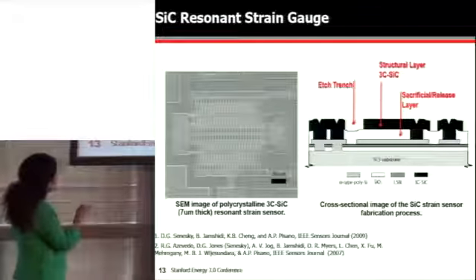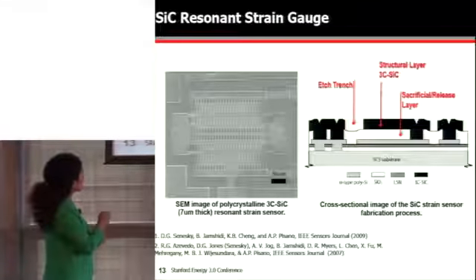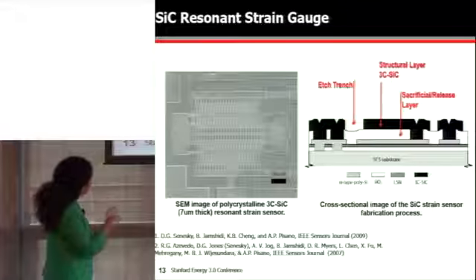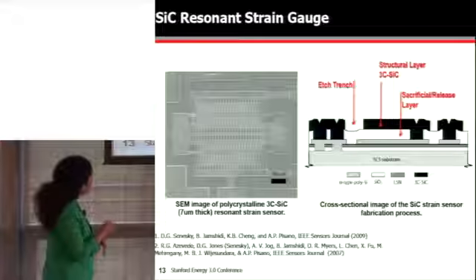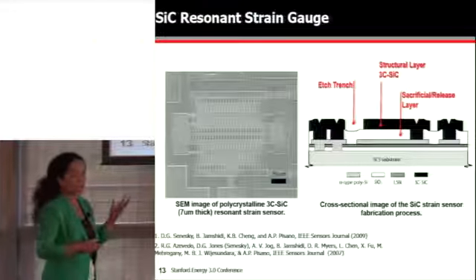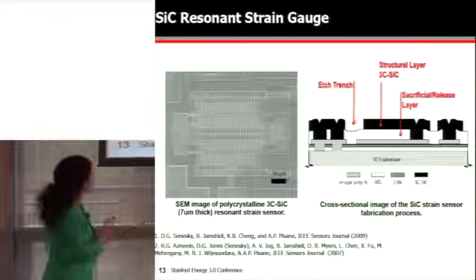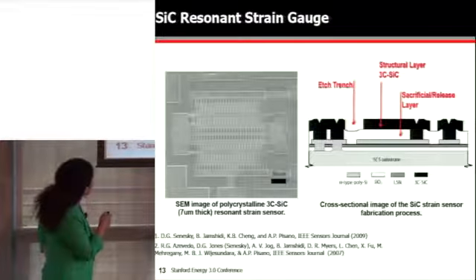And so this is some work actually showing and demonstrating the ability to manufacture and test silicon carbide sensors. This is an image of a silicon carbide strain sensor. You see the tines here. So this is a suspended structure. The scale bar here is 50 microns. The diameter of your hair is 70 microns. So this is a fairly small device.